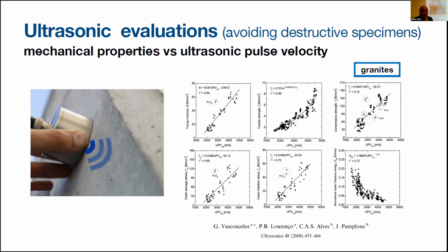For example, you see here some correlation curves between the ultrasonic propagation velocity and Young modulus, tensile strength, compressive strength, and so on. However, these correlation curves must be obtained before. These curves were obtained because several usual tests were performed, and on the same materials they also performed the ultrasonic test. And this way they found the correlation. So if you have a new material, maybe you don't have this information. So the ultrasonic test cannot always be applied.